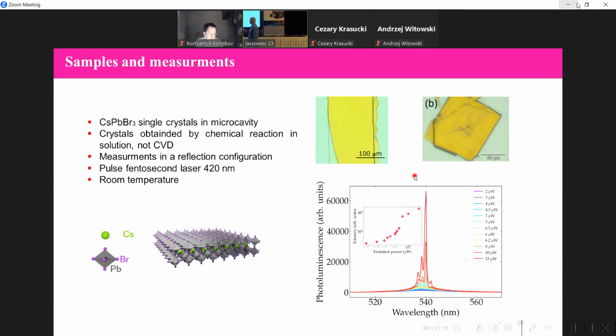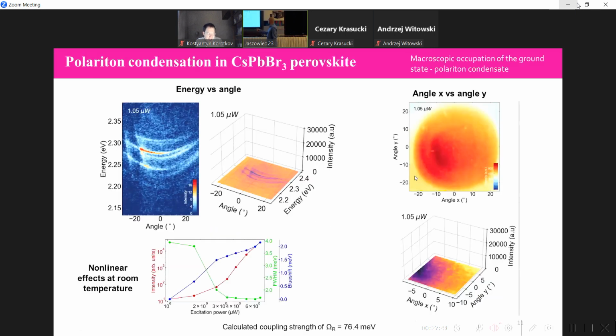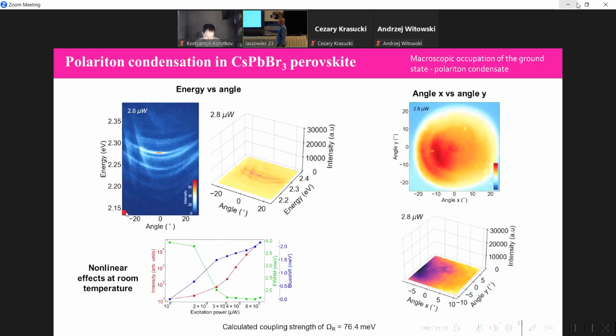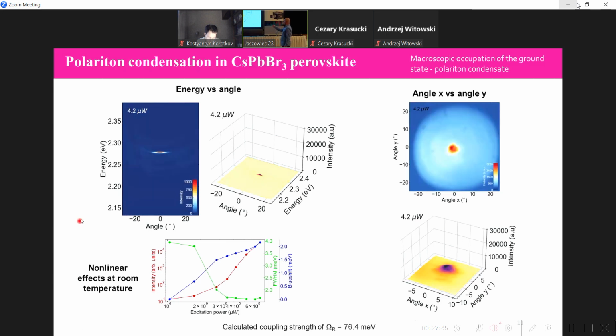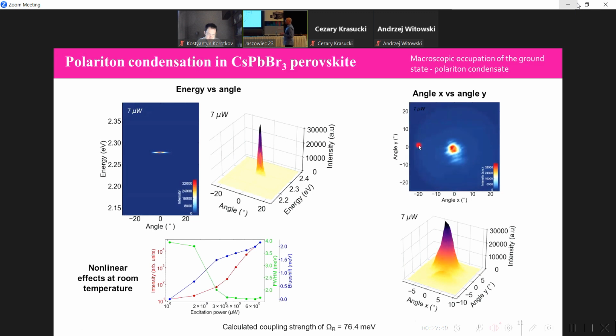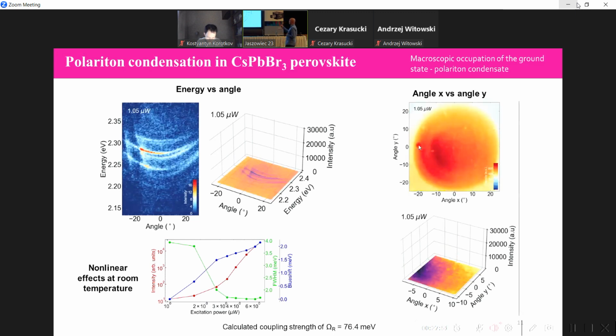And if you put this crystal in the microcavity, one can see in the angle-energy spectra there is maximum occupation, as well as if you use angle, so the reciprocal space, there is only a maximum. There is also a maximum occupation if we increase the power.